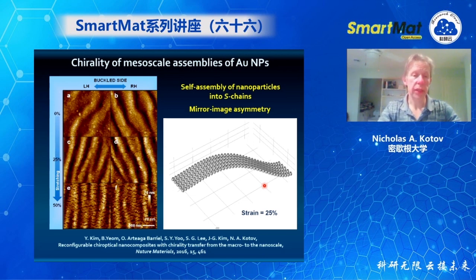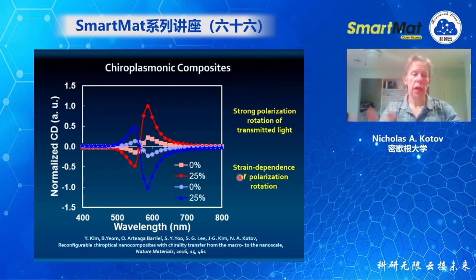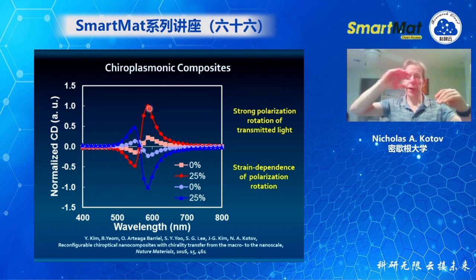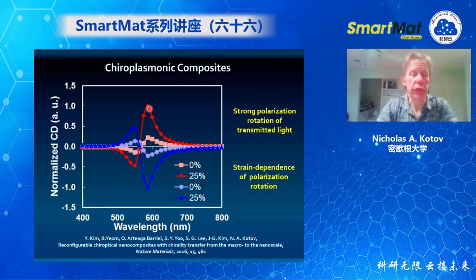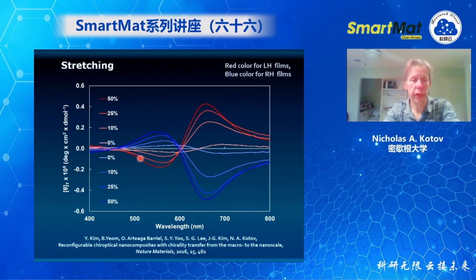And for that reason, these composite materials acquire a strong polarization rotation. So as you can see, the circular dichroism peaks here are at the plasmonic region of gold nanoparticles, and therefore they correspond to the gold chains and the plasmonic resonances in them. We looked at both peaks here at 600 and 550, and they have several contributions. Some of them have contributions of linear dichroism. But this peak at 550 has a very strong contribution of circular dichroism. And that's exactly because of the chirality of the system.